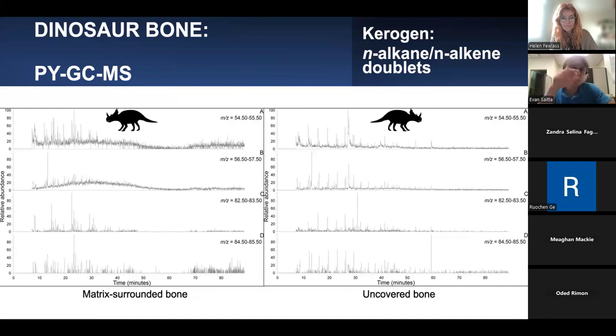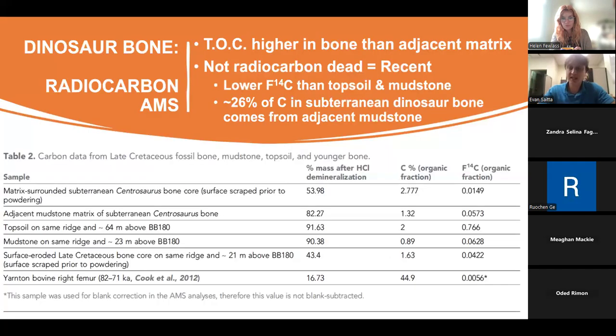So for example, if you look more carefully at the pyrolysis GC-MS data, you see that, yes, there isn't a clear fingerprint of proteinaceous material or high organic content, but we do see organics such as kerogen, as evidenced in these alkane-alkene doublets. And this kerogen is often described as a geopolymer. It forms over long periods of time through diagenesis. And so even though many of the amino acids are relatively recent, there is some relatively older organic material, perhaps not Mesozoic, but definitely not just completely modern.